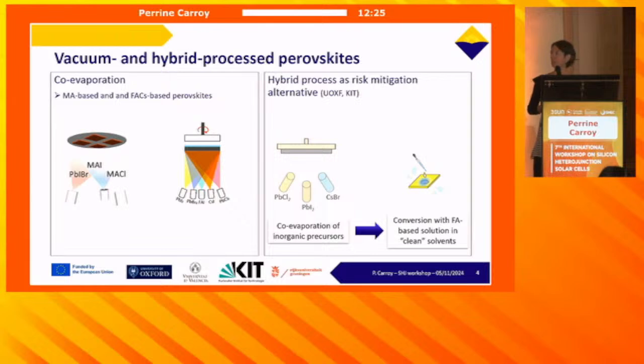As I was saying, for the perovskite top cell, we are mainly focused on vacuum-processed perovskite, mainly co-evaporated materials where all the perovskite precursors are sublimed together. The partners develop either methylammonium-based perovskite, but also formamidinium cesium-based. And we are also developing, as a risk mitigation approach in case we don't reach sufficient efficiency with the all-vacuum process, the hybrid process where the inorganic precursors are first processed in vacuum and then the organic precursors processed in solution, which we still find acceptable in terms of environmental friendliness because the solvent you need for this organic step can be only alcohol-based, so you still avoid the nasty solvents you use when you fully process the perovskite with solution.